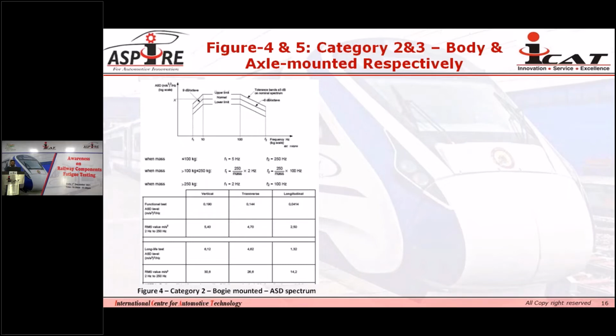For the lower frequency, we have to calculate 250 divided by mass of the test component into 2. It will give us the lower frequency, and for the higher frequency, 250 divided by mass of the component into 100. It will give the higher frequency. And if the weight of the test sample or test component is more than 250 kg, in that case, again, the frequency is fixed, that is 2 Hz to 100 Hz.